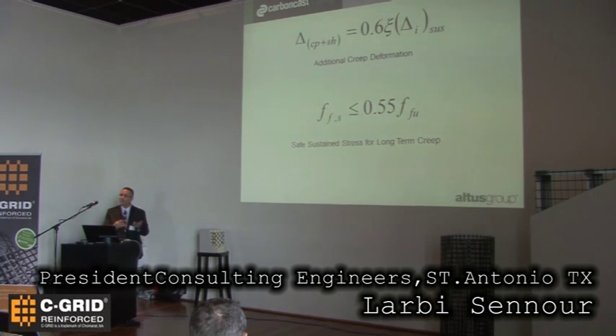The way we tested it, we started loading a grid at 0.4, 0.5, 0.6, 0.7, and then kept it for a whole year, and we saw that it broke at 0.6, but it didn't break at 0.5. So we tested 0.55, and it didn't break, so that's where that 0.55 came from. It's not analytical, it's all by test.